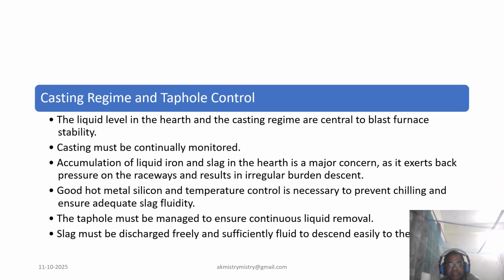Since the blast furnace is a continuous process, the casting regime must match the rate of production. Continuous liquid removal prevents liquid accumulation, which causes instability. The goal of zero fluctuation requires minimizing hot metal quality variation. Especially, the silicon content should fluctuate less than 0.15%.